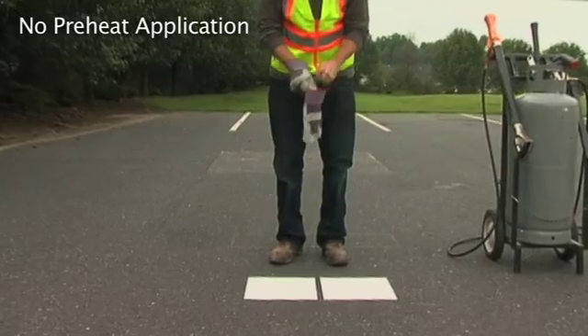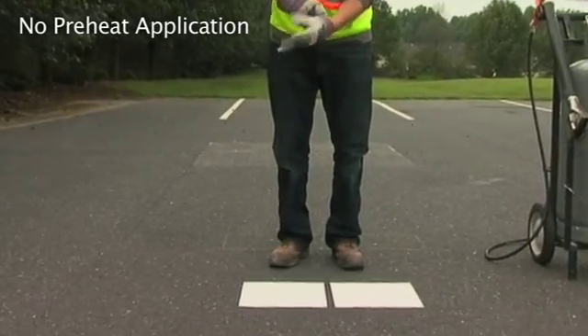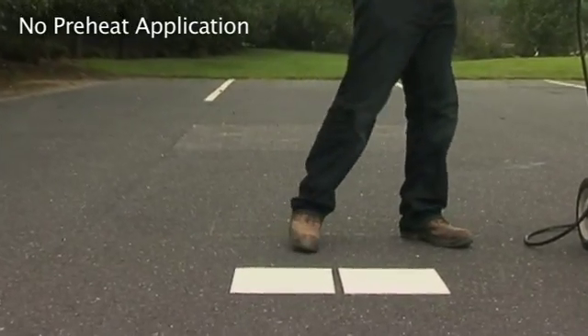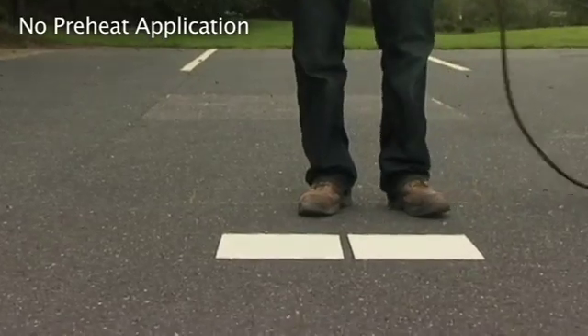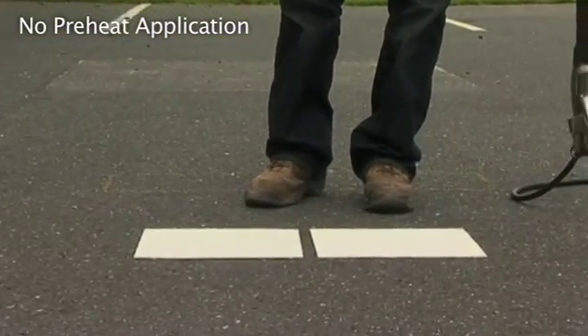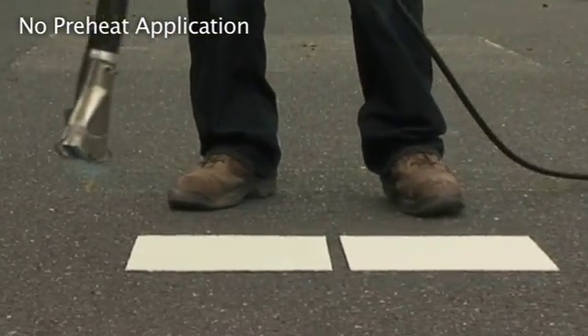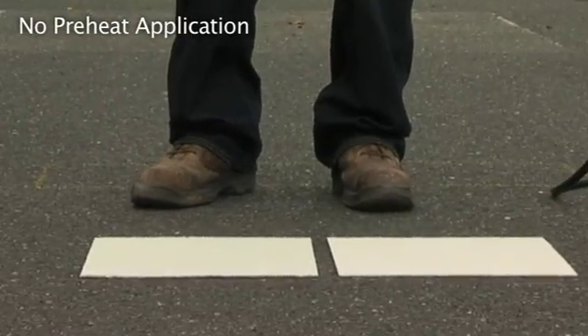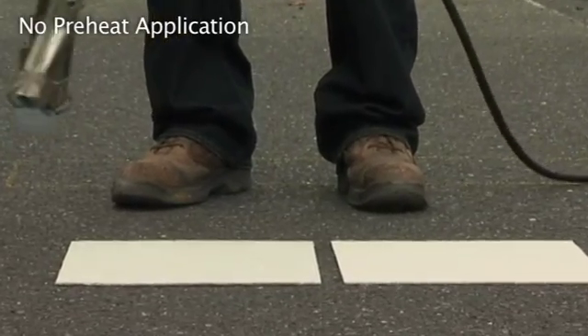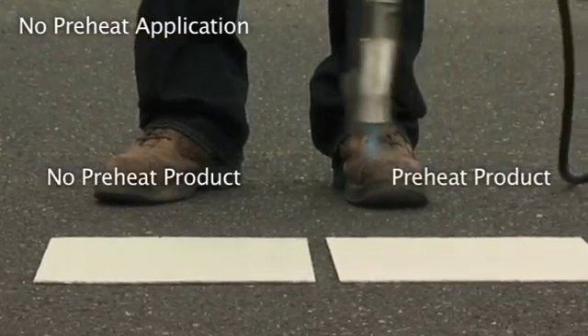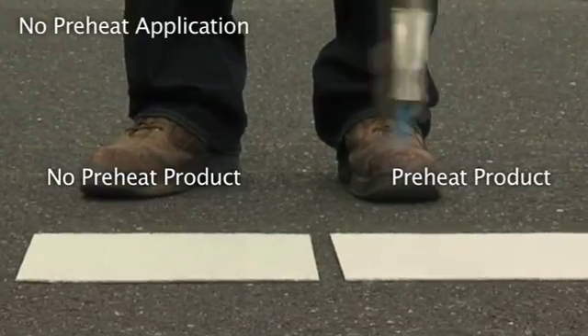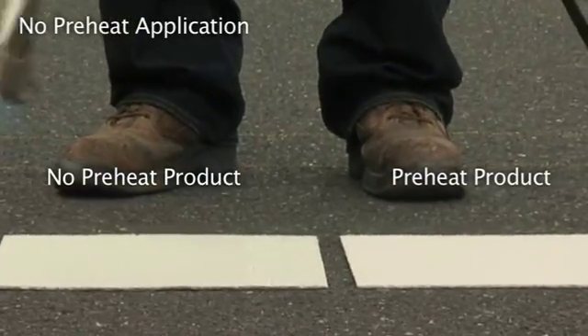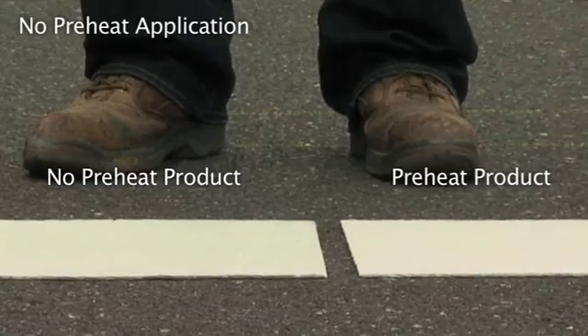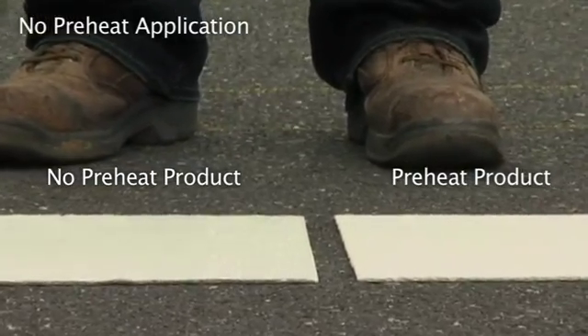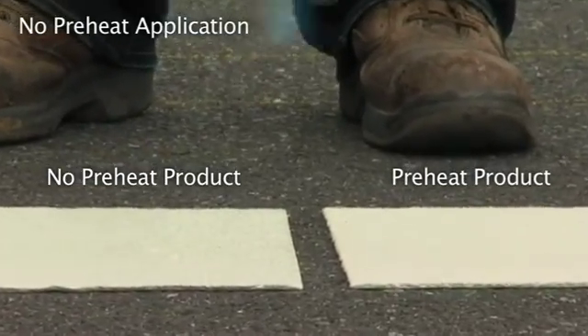The material on the left is a no preheat product, the material on the right is a preheat product. Using the Flint 2000 EX heat torch, heat is applied using a sweeping motion approximately 2 feet wide and 6 to 8 inches above the material in order to apply equal amounts of heat to both product types. Based on the manufacturer's application instructions for a no preheat product, heat is applied equally to both products until the indents in the no preheat material on the left are closed.